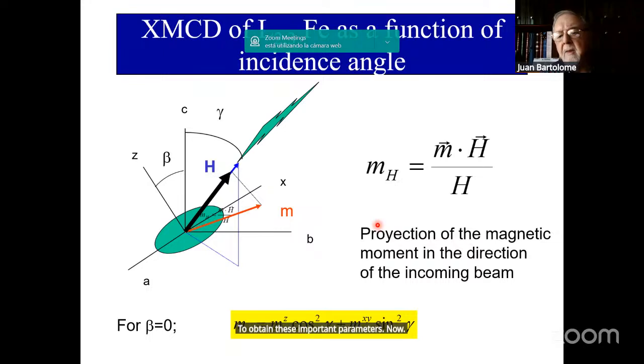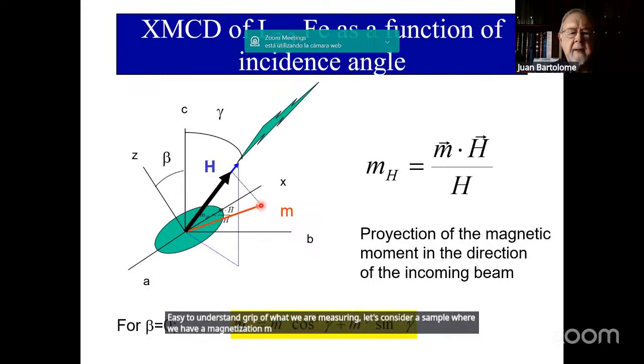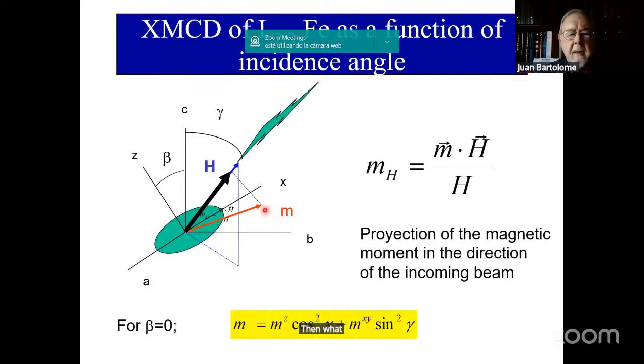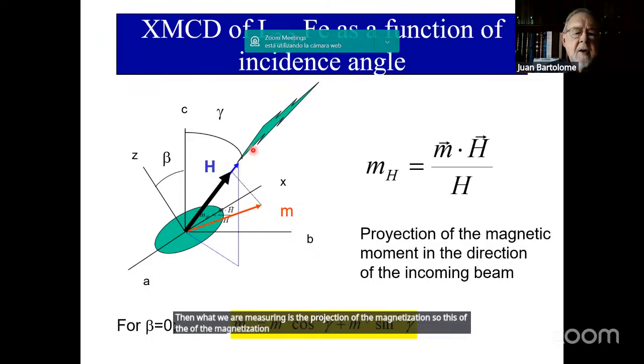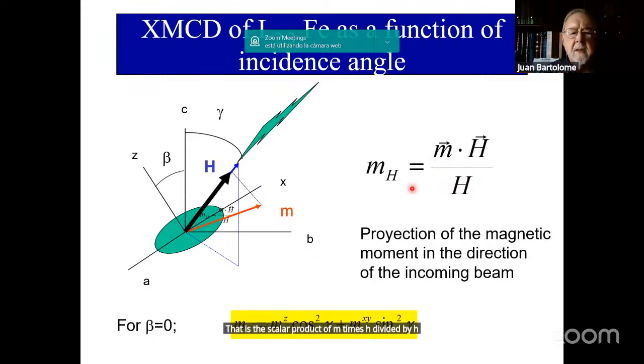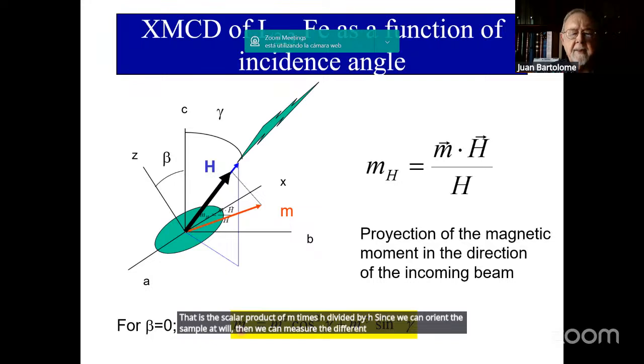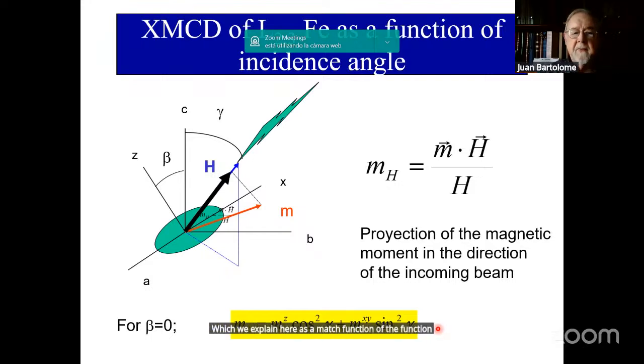Now, to get an easier grip of what we are measuring, let's consider a sample where we have a magnetization M, and then we apply a field and shine the synchrotron radiation along the direction of the field. Then what we are measuring is the projection of the magnetization into the direction of the field. That is the scalar product of M times H divided by H. Since we can orient the sample at will, we can measure the different components of the total magnetization, which we explain here as a function of the angle of incidence.